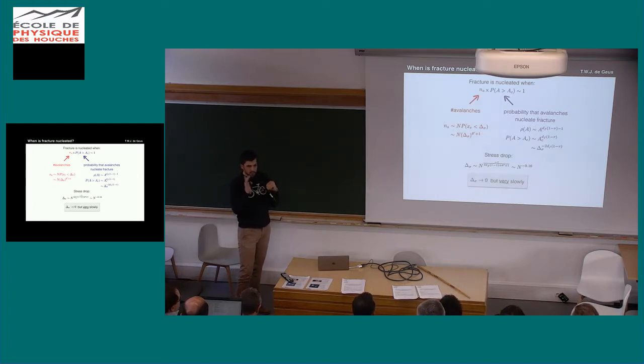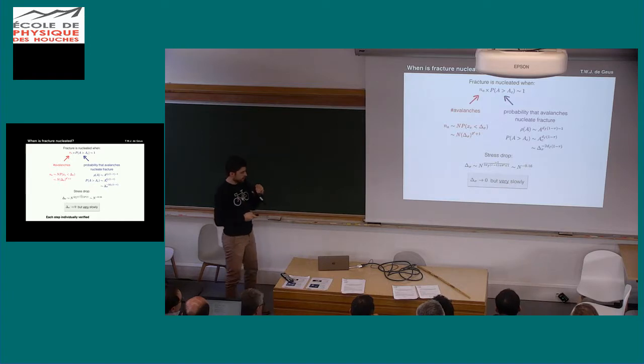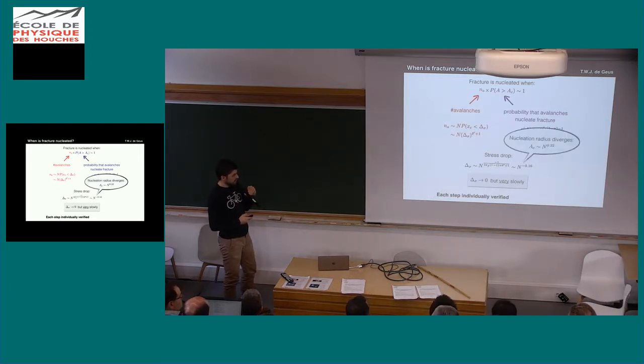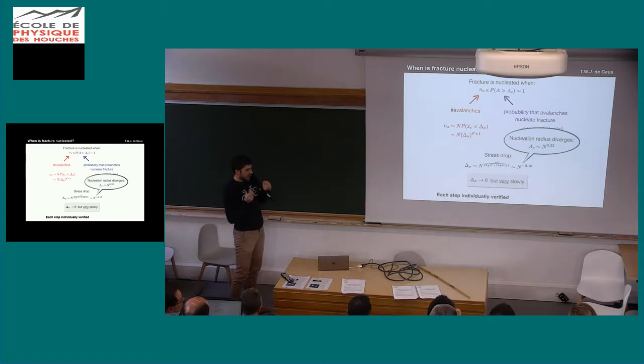So actually, if we wave our hands, we can estimate that in any realistic system, the stress drop will actually persist. A disclaimer here is that the scaling argument, we can verify every step individually. So that makes us pretty confident. And a bit of a surprise here is that when we reinsert this Griffith criterion, we find that the nucleation radius is actually governed by the system size and it diverges with the system size.